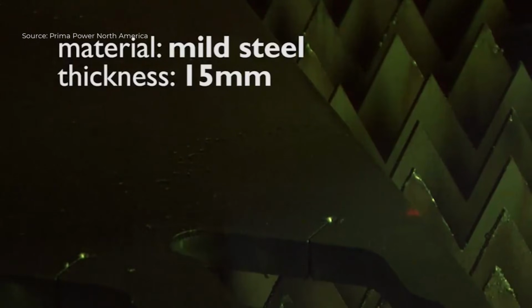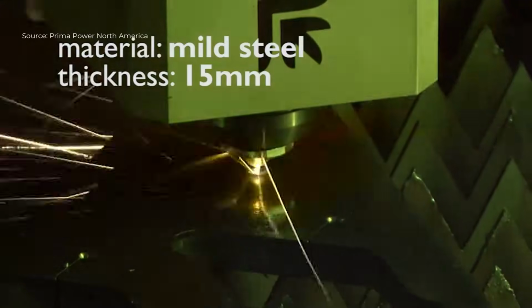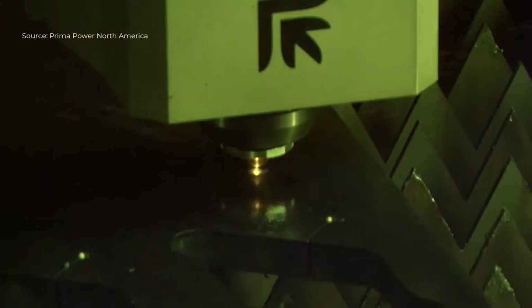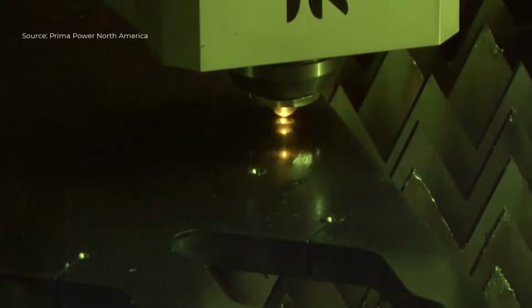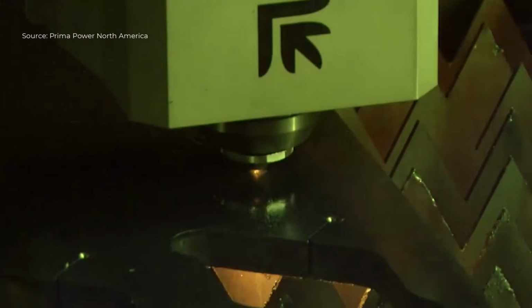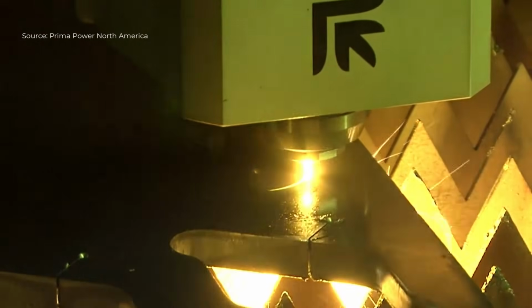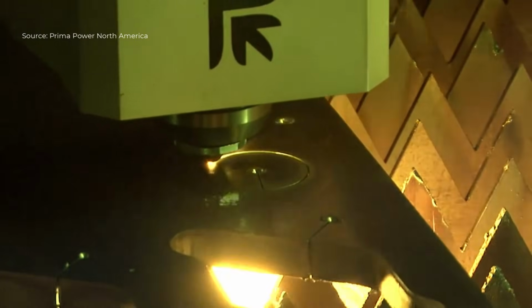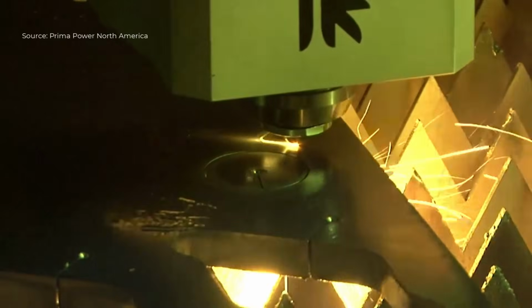The demonstration continues with mild steel sheets of increasing thickness, beginning with 15 millimeters. For this material, the advanced piercing devices play a critical role. The laser performs a carefully controlled piercing cycle to penetrate the thicker plate without causing excessive spatter or surface damage. Once piercing is complete, the cutting head advances along the programmed path at a reduced but optimized speed. The fiber laser maintains stable power output, allowing the machine to produce straight edges and uniform cut surfaces even in mid-thickness mild steel. The reduced cycle time highlights how the Platino fiber improves productivity without compromising quality.